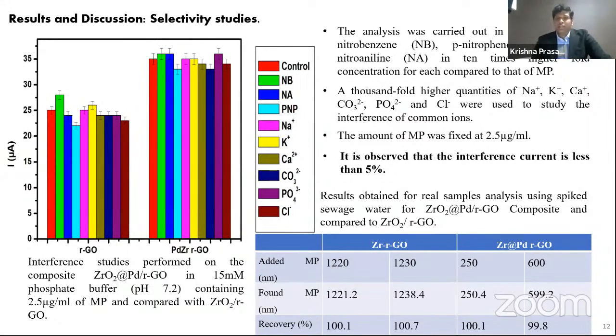Moreover, to ensure that our material works in real world applications, we have tested real world samples. That is, we have collected sewage water from our campus, pre-filtered it to remove any particulates, spiked it with methyl parathion, and tested it with both the electrochemical method and the tried and tested GCMS, that is gas chromatography and mass spectrometric methods. And we have found that our samples give very good recovery rate and a very small range of errors.